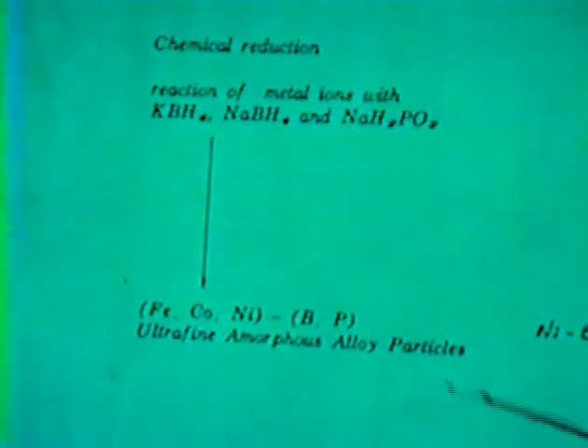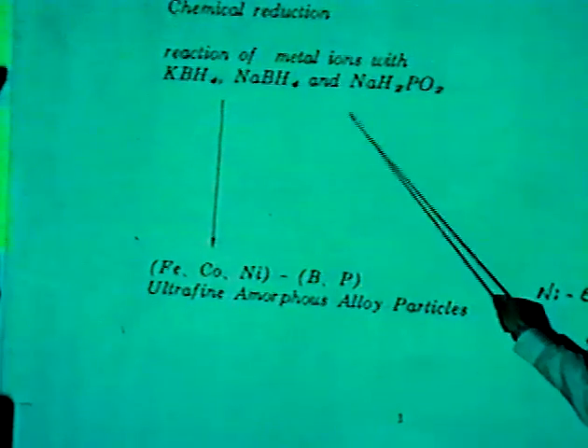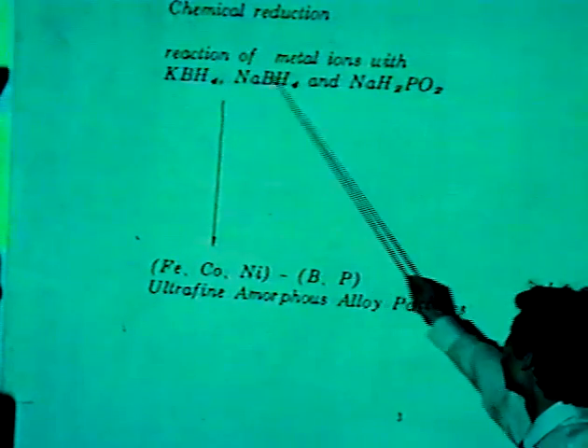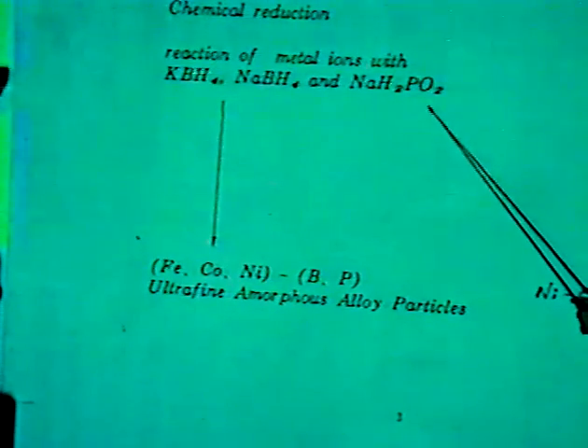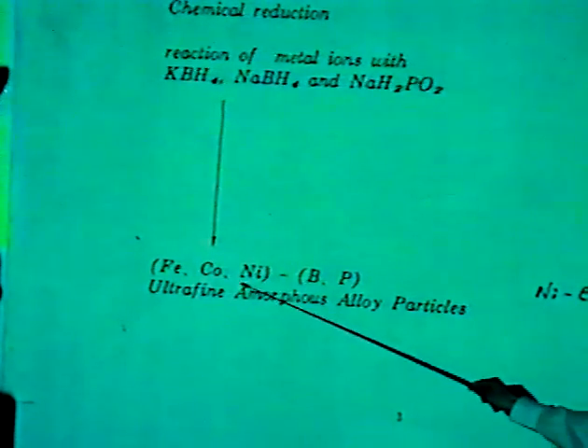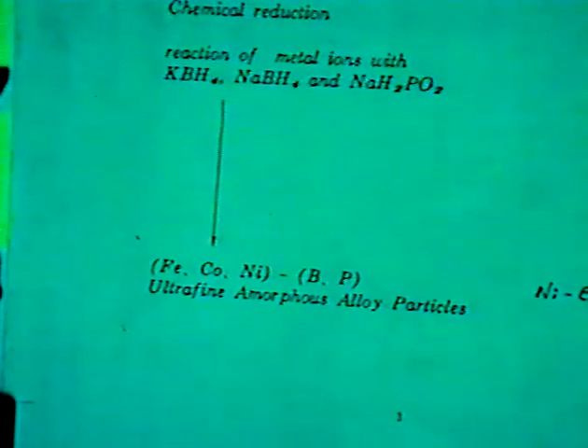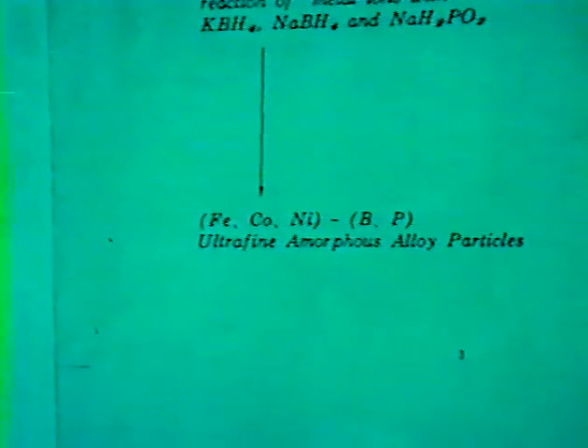It has been reported that some amorphous alloys can be produced by the reaction of metal ions with potassium borohydride in aqueous solution. The amorphous alloy produced by this chemical reaction is in the form of ultrafine particles. In fact, Okamoto has studied the nickel boron and nickel phosphorus samples for hydrogenation of some organic compounds.